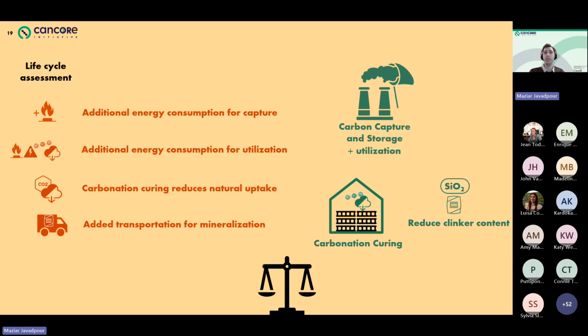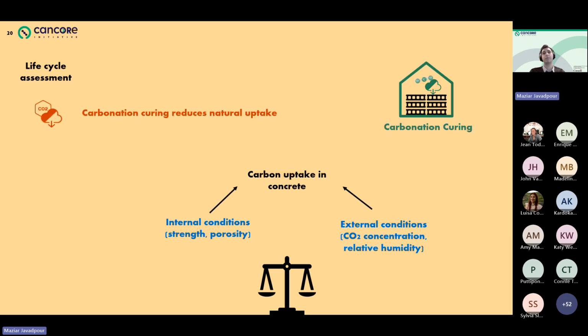But before we get into that, we need to zoom in on the natural uptake question because it's more complex than it might seem. Carbon uptake depends on both internal and external conditions, and as Sylvia put it. So higher porosity, talking about internal conditions, higher porosity and lower strength concrete is generally going to take up more CO2 during its life and end of life than a stronger concrete and a higher compressive strength concrete because of how denser the stronger concrete is.